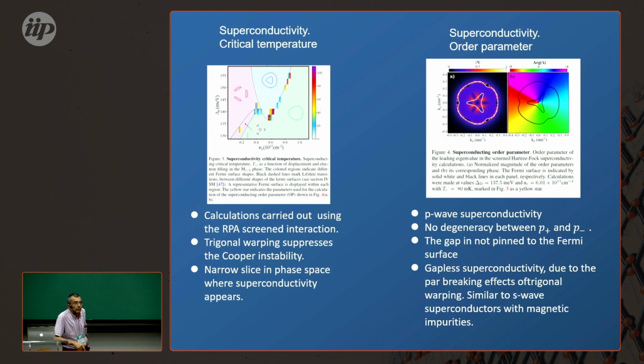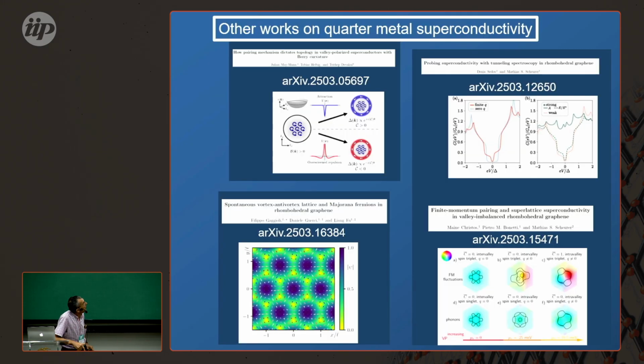It means that you don't have the Cooper singularity to help you. Moreover, most likely the superconductivity is gapless because it's not pinned to the Fermi surface. It cannot be pinned to the Fermi surface because if K is at the Fermi surface, minus K is not going to be there. And so in some way trigonal warping plays the role of a pair-breaking perturbation in this p-wave superconductor.